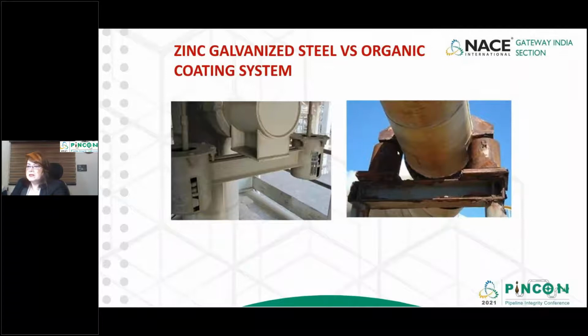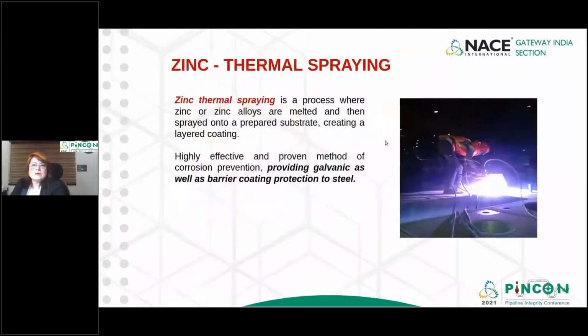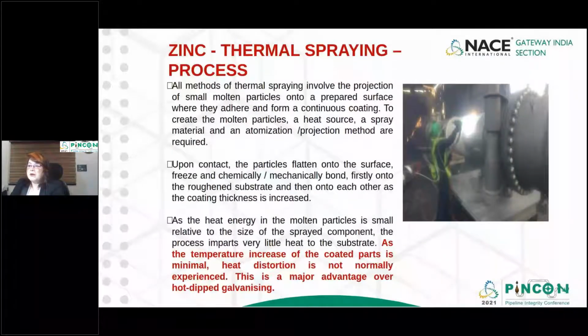Similarly, in the case of pipe and pipe supports, zinc or zinc alloys are melted in the zinc thermal spraying process and then sprayed onto a prepared substrate, creating a layered coating giving galvanic as well as barrier protection of steel. As the heat energy in the molten particles is small relative to the size of the sprayed component, the process imparts very little heat to the substrate. As the temperature increase of the coated parts is minimal, heat distortion is not normally experienced. This is a major advantage over hot dip galvanizing.